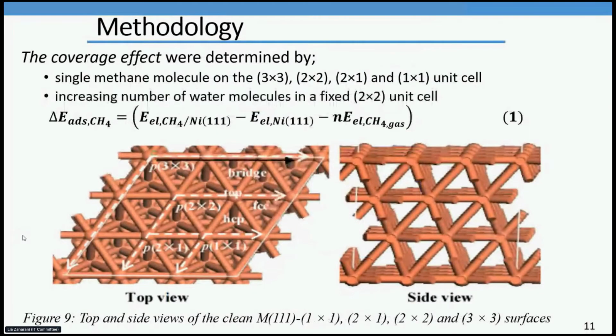The coverage effect was determined by, for the methane, a single methane molecule on a 3x3, 2x2, 2x1, and 1x1 unit cell to replicate different coverage of 0.1, 0.25, 0.5, and 1.0 monolayer. For the water molecule, by increasing the number of molecules in a fixed 2x2 unit cell from 1 to 4.